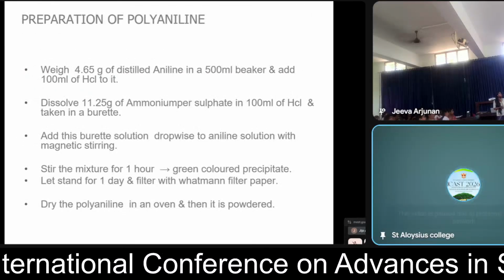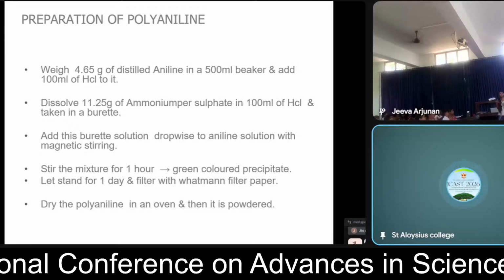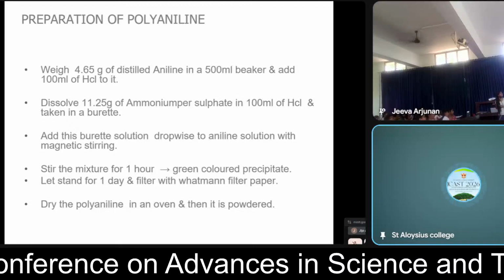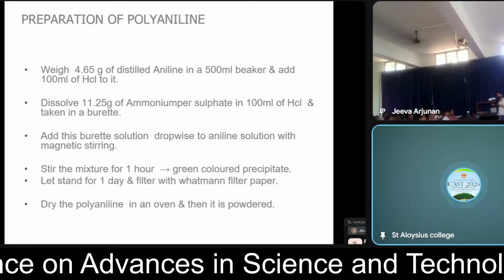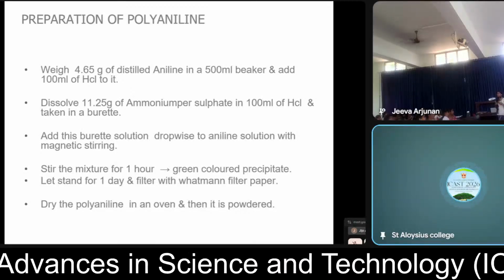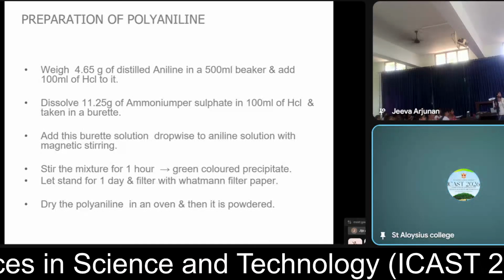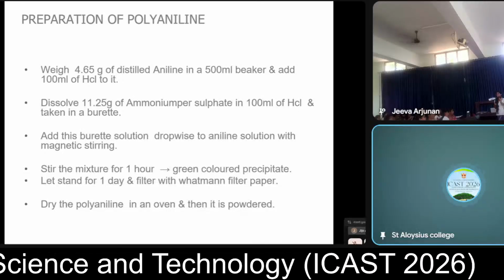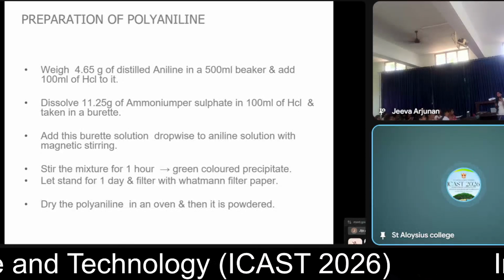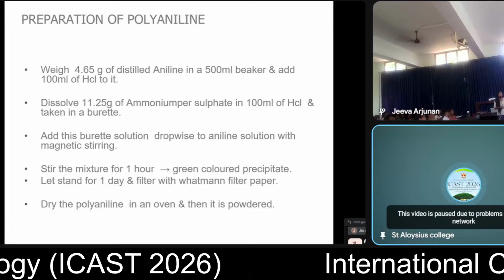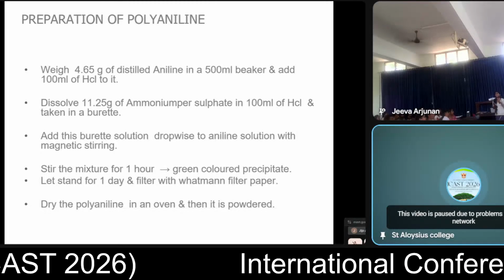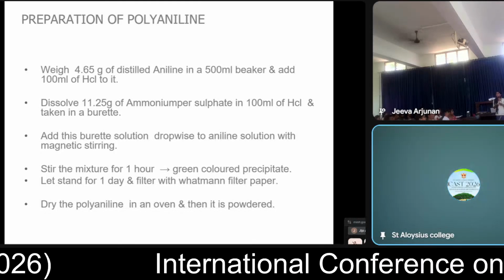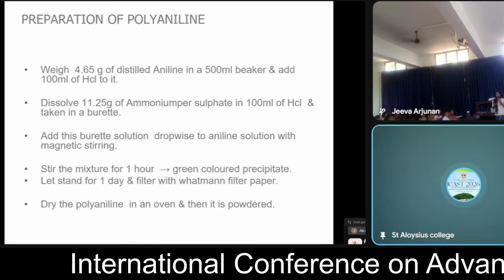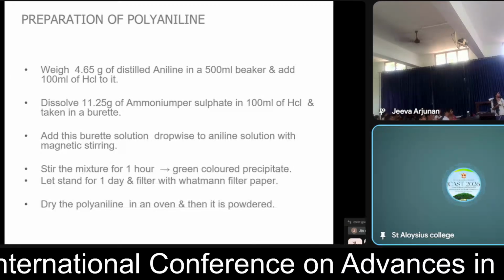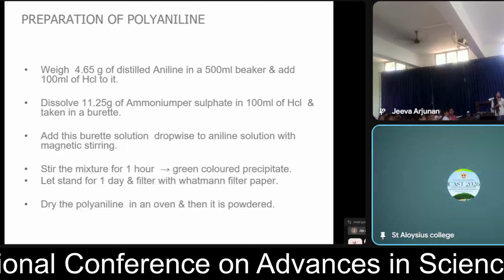For the preparation of polyaniline, we take 4.65 grams of distilled aniline and HCl solution in a beaker. To it, we add ammonium persulfate dissolved in HCl from a burette, dropwise to the aniline solution with constant stirring. After 1 hour we get a green colored precipitate, which is polyaniline. We filter it, dry it and powder it. So that's how we obtain this polyaniline.